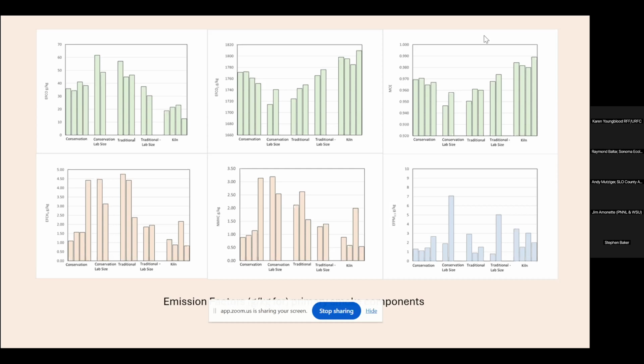And then for the PM2.5, this is based on the filters. The conservation burns were, I would say, kind of similar to the traditional and the kiln. There wasn't really a significant difference between the three types. But all of these numbers are very low for emission factors. Generally, emission factors for wildfires range anywhere from 3 to 10, and these were all down in the 1 to 3 range.